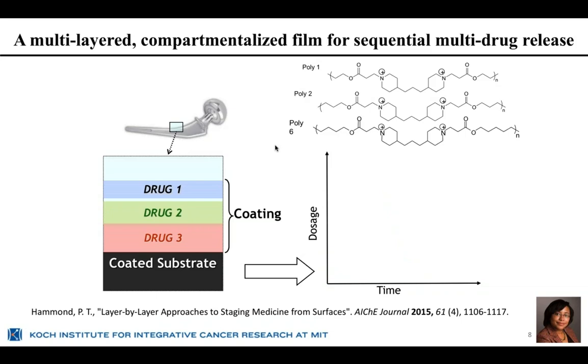On top of that, we get beyond that limitation of drug loading. Rather than having just a 1 or 2 weight % loading before phase separation, here the thermodynamic rules are essentially charge compensation. So we can get loadings that are as high as 30, 40, or 50%, depending on the architecture of the film and what we're absorbing. So we can get very compact and dense amounts of material into very thin films.